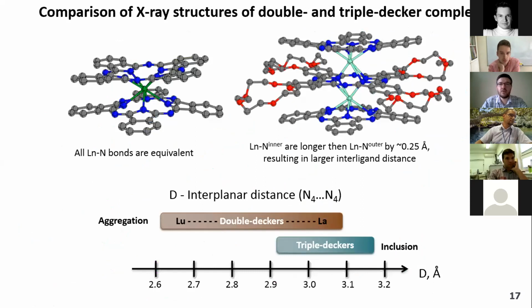If we take a look at structures of double- and triple-decker complexes, we can see that the distances between ligands in triple-decker complexes are a quarter angstrom larger than in double-decker complexes, because of the bridging nature of the internal ligand, and thus the bonds from the metal to this bridge are larger than from the metal to terminal ligands. So we may think that in the case of triple-decker complexes we observe intercalation, and we should observe the same intercalation in the case of double-decker complexes of the early lanthanides, which have a similar